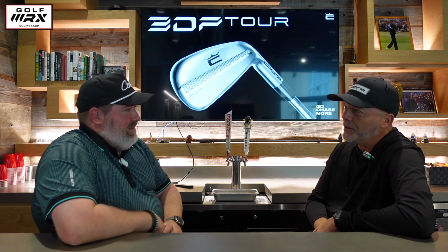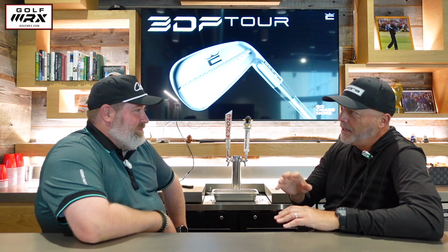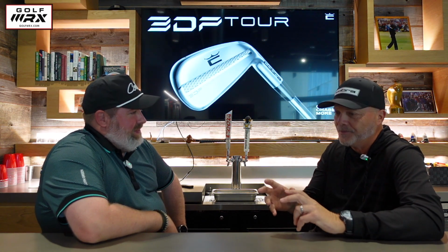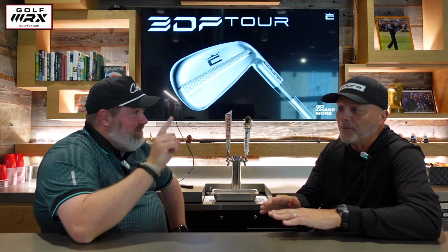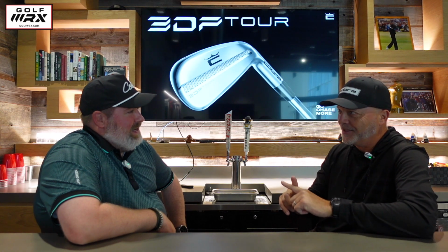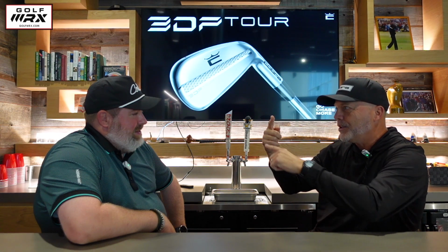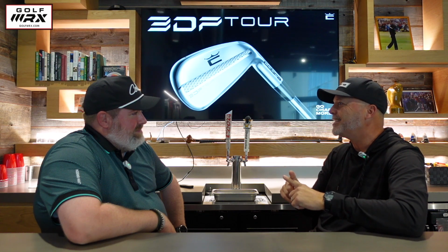Yeah, we work very closely with the vendor. It's funny, we'll go back, nerd alert, back one step, just to print that thing. It gets printed in a toe down, hosel kind of in this orientation, and it's 2,600 layers from start to finish. From nothing to it's done, okay? And getting the lattice built correctly on the inside, because you're looking at it, you can't build a lattice like this, okay? It'll collapse. You have to build it at least at 45 degrees.